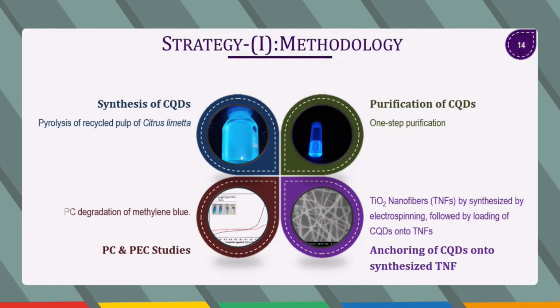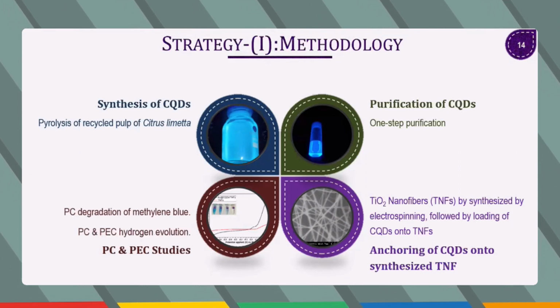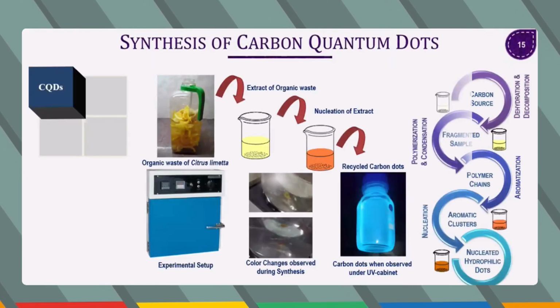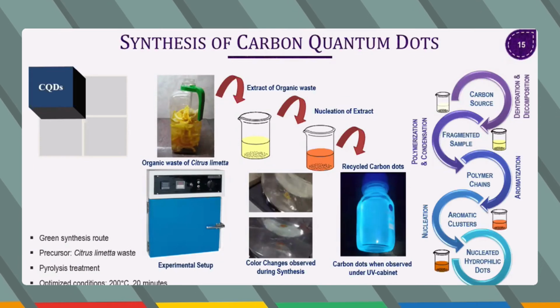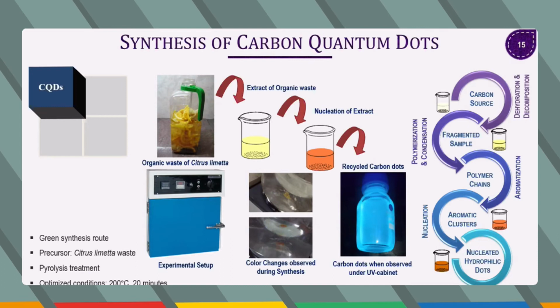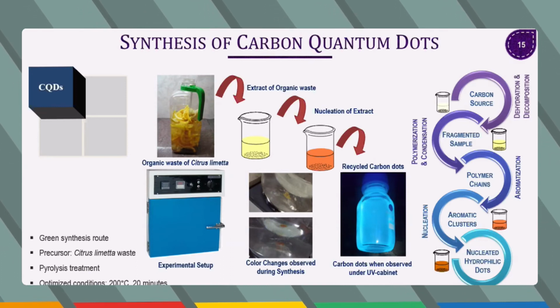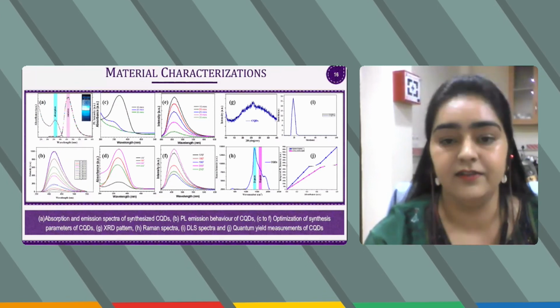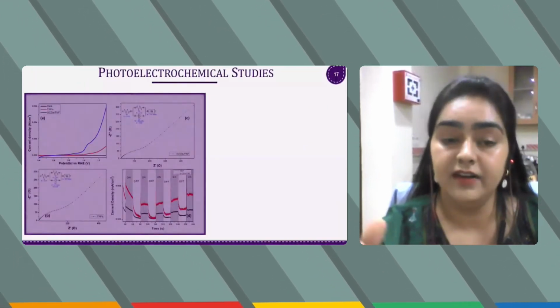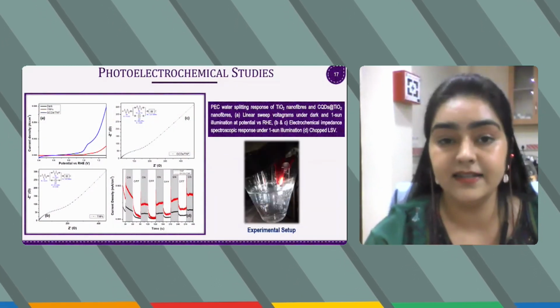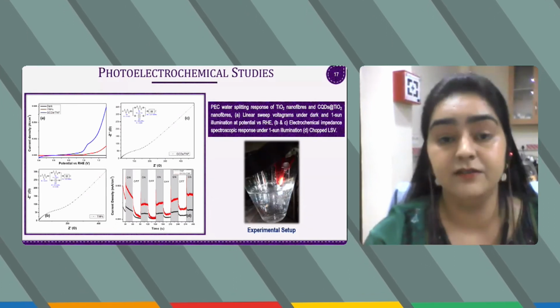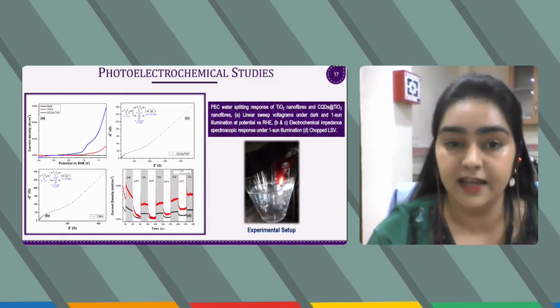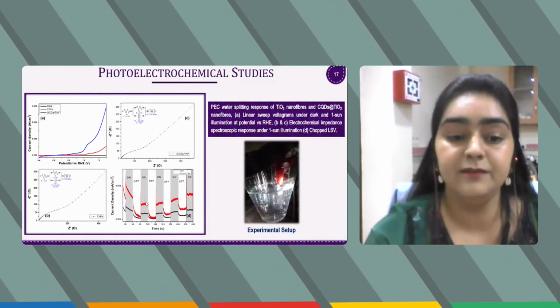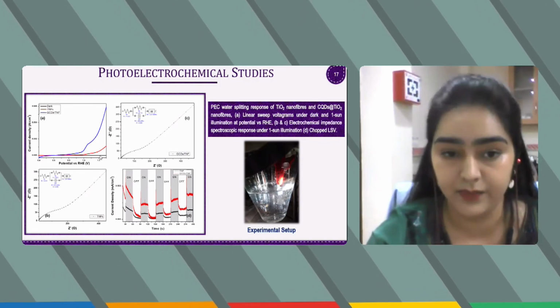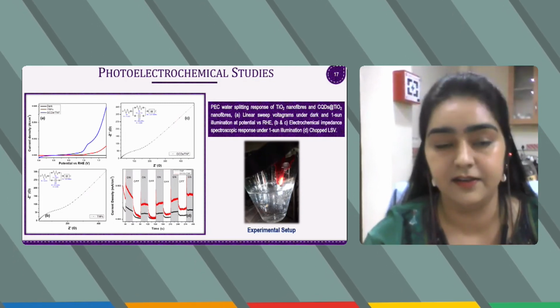Firstly, we have synthesized carbon quantum dots from waste. This is basically a strategy in which we are producing nanomaterials from waste. We took the organic extract of Citrus limetta, that is mosambi fruit, pyrolyzed that extract and converted it into highly fluorescent carbon quantum dots. These carbon quantum dots have been fully characterized, from the optical to morphological and other structural characterizations. Further, we investigated this material, which acts as a visible sensitizer and helps us absorb the visible light of the solar spectrum. With these results, it can be concluded that the material produces a high photocurrent of 6 milliampere per centimeter square, and the on-off characteristic also shows its better performance for this application.